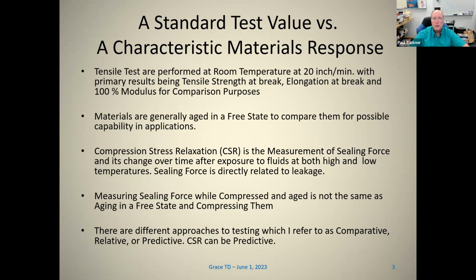One of the things I want to talk about initially is a concept I've developed: the difference between a standard test value versus a characteristic material response. I use tensile test as an example of a standard test value, where tensile tests are typically performed at room temperature with a strain rate of 20 inches per minute, with the primary results being specific values: tensile strength at break, elongation at break, and percent modulus.